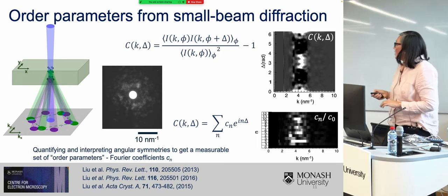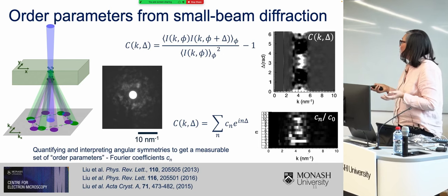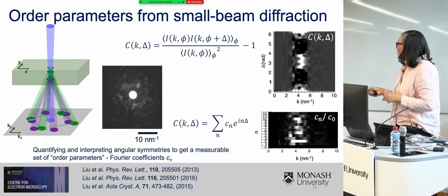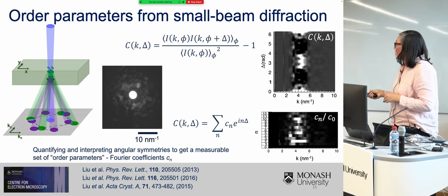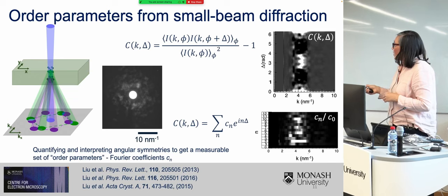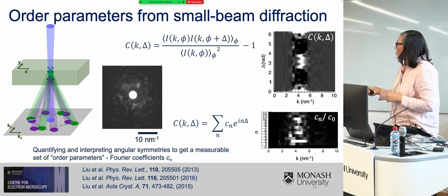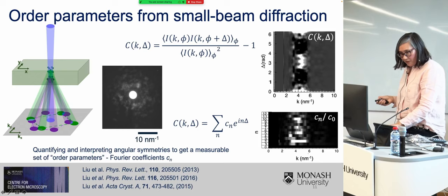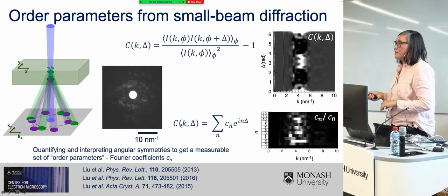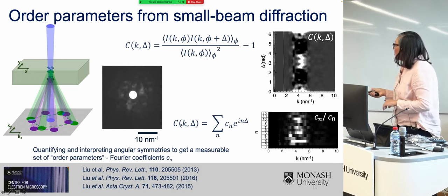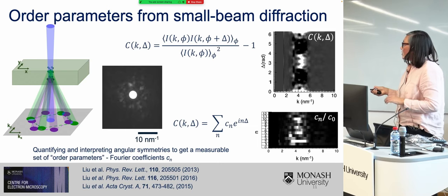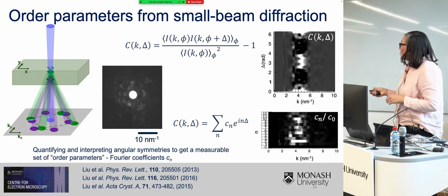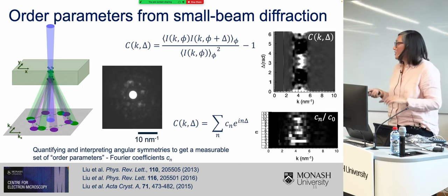So keeping this in mind, I set out to try to measure some kind of order parameters from my small beam diffraction. Here you can see the geometry for scanning electron nanodiffraction, where I have my focused beam tuned to the size of a coordination polyhedron, and I scan it across the surface of my specimen. If I just play this video, you can see the kinds of diffraction patterns that I actually obtain. You can see that the speckle patterns change from area to area quite quickly. Sometimes they have strong angular symmetries in them, and sometimes they seem perfectly disordered.